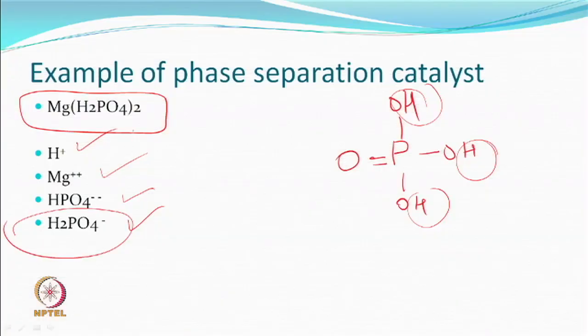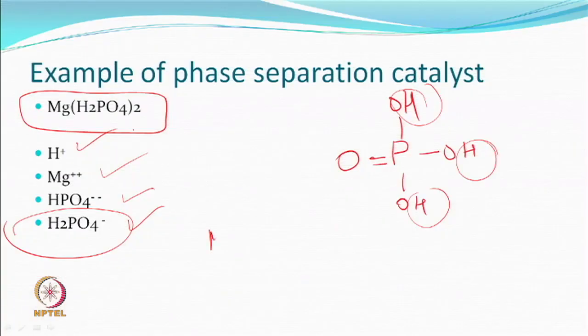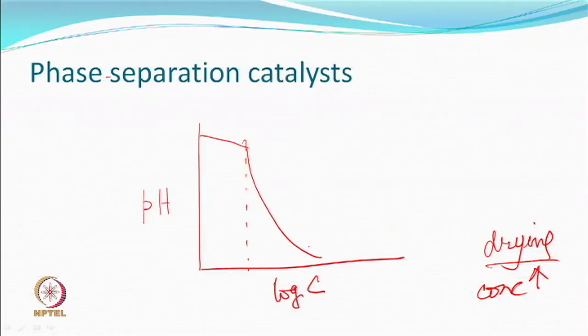And as you dry, at some stage, the solubility of the magnesium hydrogen phosphate is less. In water, it precipitates, and the other one becomes more active. In the beginning, most of this is present, and so it works like a weak acid. The moment the other compound, which is magnesium hydrogen phosphate, has a low solubility, it precipitates, and therefore equilibrium shifts and more protons are produced, and we will get a phase separation and a pH change which will look something like this.